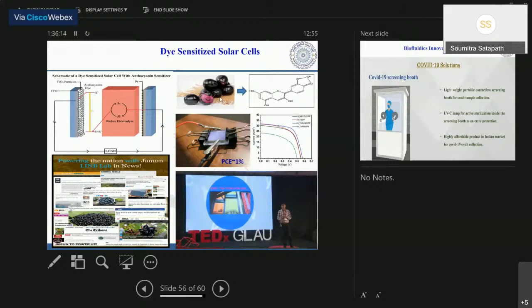So we were curious: can we use this jamun for making solar cells? We just used the jamun extract, put in an ethanol extract. We pluck the jamun from IIT here; we have a lot of jamun trees on the campus. Pluck it, put it in ethanol, get the extract, and then make a solar cell out of it. To our surprise, we got an efficiency of 0.5%. Then we continued our work by removing some impurities, and we have been able to improve the efficiency to 1%.